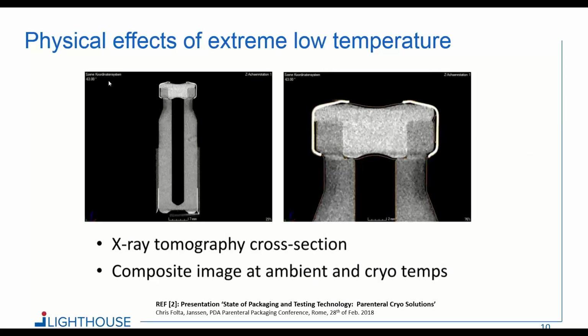So here's a slide from a presentation given by Chris Folta at Janssen at a packaging conference a couple of years ago. And this is a similar X-ray tomography cross-section as the last slide, but now you see the full vial. And what's interesting here is you can see these interface gaps start to appear. And you have to look closely, but I've put up a red circle here to draw your attention to a point where the rubber stopper has actually started to pull away from the inside of the vial neck there. So again, physical evidence that you see these interface gaps start to appear.